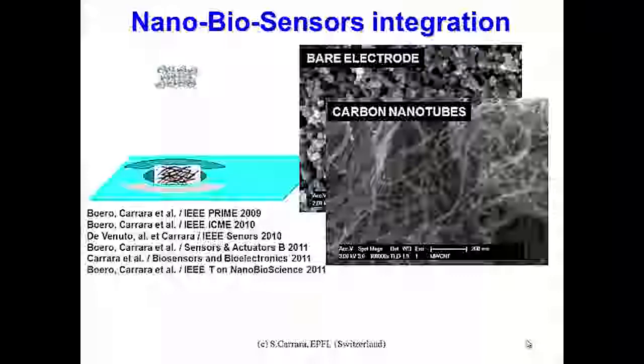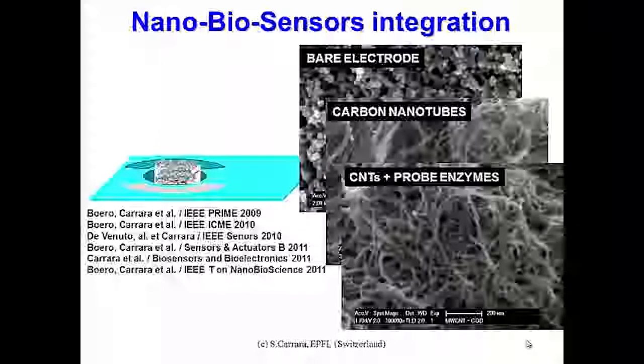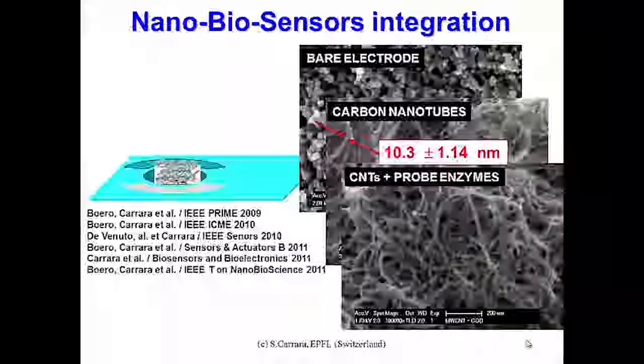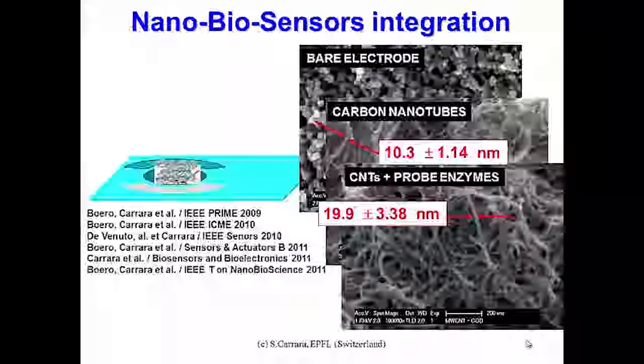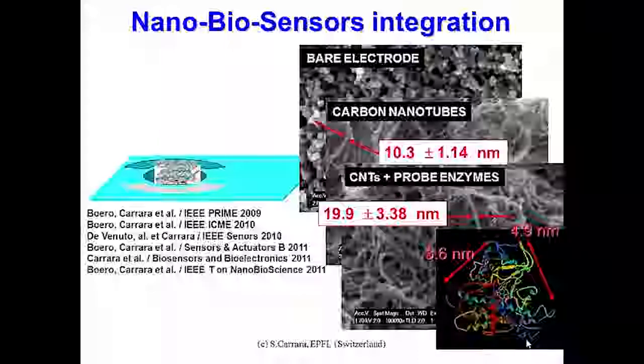And then we can repeat the same operation to drop cast our enzymes on the electrode, and as you can see, the features of the carbon nanotubes slightly change. We can measure the diameter of the carbon nanotube fiber before and after the biofunctionalization, and compare this size, which ranges from roughly 10 nanometers up to 20 nanometers, with the expected size of the enzymes. In this example, we have the cytochrome P450, which is a metalloprotein.